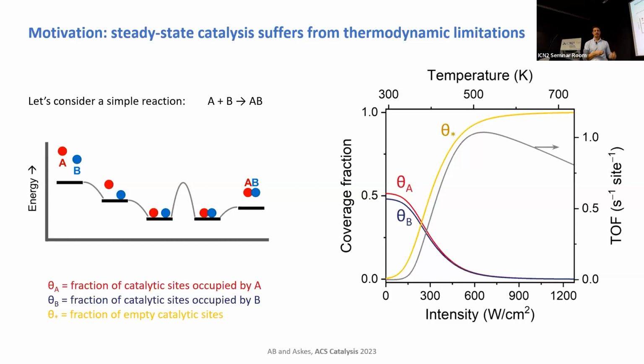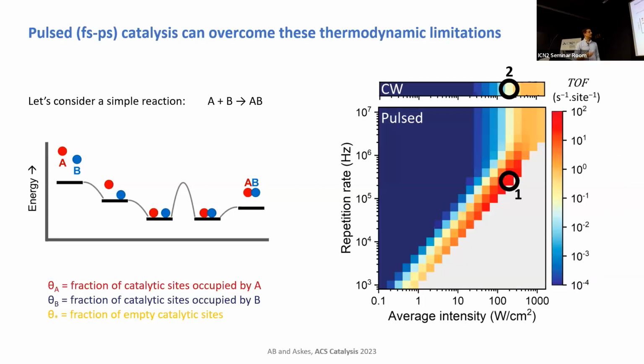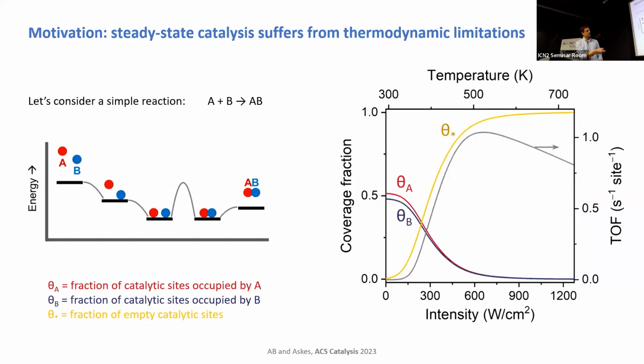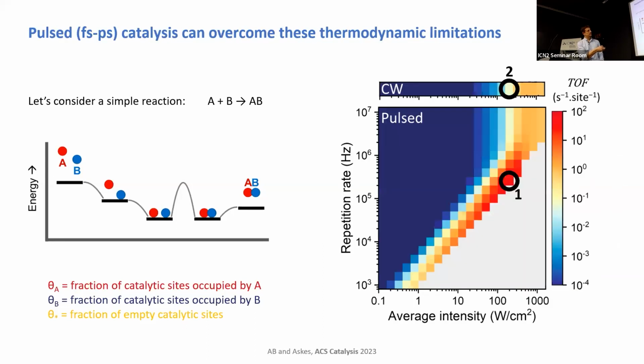Can we do better than the steady state catalysis? So this is the kind of calculations that we did, and in fact, we can. So what I'm plotting here is the turnover frequency, exactly the same plot that you see here. So for A and B, here you see that the turnover frequency under steady state illumination or steady state temperature has a maximum. And you see the same here.